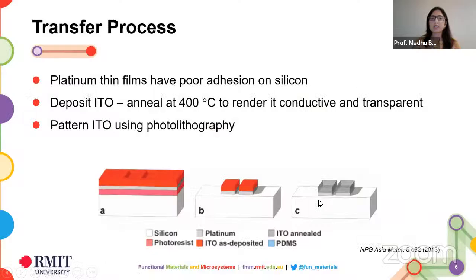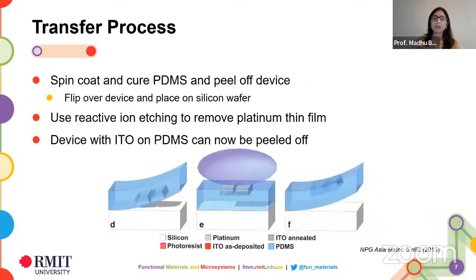So what you see, for instance, here in this figure C is basically patterned ITO, sitting on top of platinum, which is sitting on top of your silicon substrate. Now, on top of this, if you spin coat and cure PDMS and you peel it off, because like I mentioned earlier, the platinum is not stuck very well to the silicon, you can essentially just peel off the entire device off the silicon surface.